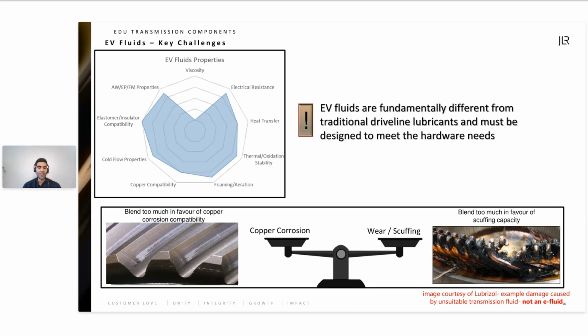And the images you see there, there's always a balance between copper corrosion and wear and scuffing on our gears and our bearings. It's really important that we find that sweet spot, because the same additives that are not corroding copper are protecting the gears and surfaces from wear. And there's a big demand for OEMs and lubricant suppliers to understand this region of application for extreme pressure and anti-wear additives.